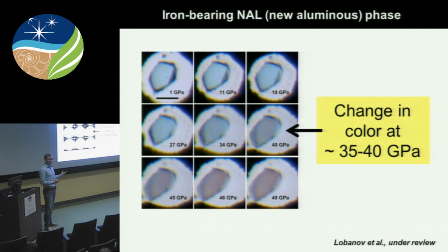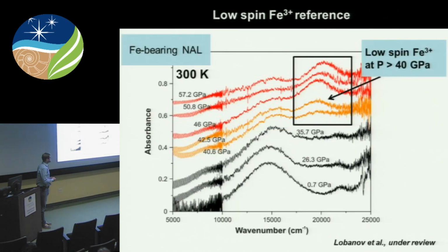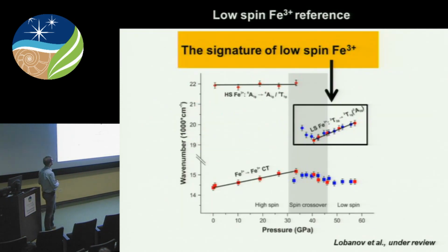So if we now just look at optical images of this NAL mineral as a function of pressure, we will see that at approximately 40 GPa, there is a pinkish tint appearing literally out of the blue to the color of this mineral. So this already, just as in siderite, tells us that something's going on with its electronic structure. And of course, this pinkish tint is recorded in the absorption spectrum.